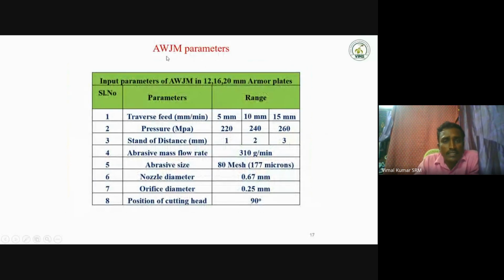So these are the abrasive water jet machine parameters. First is the traverse feed. The range is specifically designed for armor grade steel. Because we need to cut the thick, high strength material, we need to reduce the feed rate. Then only can we easily achieve the depth of penetration. So the traverse feed is 5 mm, 10 mm, 15 mm.